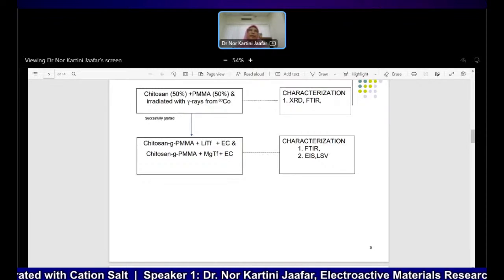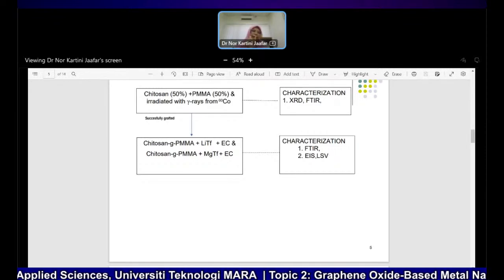Starting from the electrolyte preparation, and then when we fabricate devices like batteries or supercapacitors, and when we test LSV and so on, we must do it in a glove box, which also must be in good condition. Sometimes if not maintained well, it can make our lithium salt and lithium film inside the glove box get destroyed. That's why I tried with my student using another salt, magnesium.